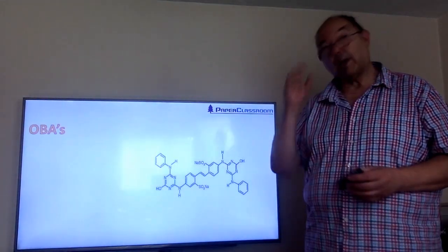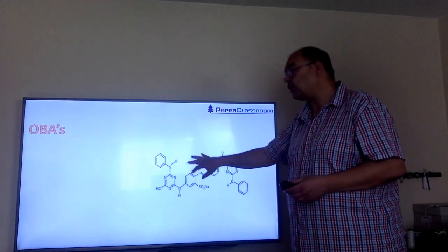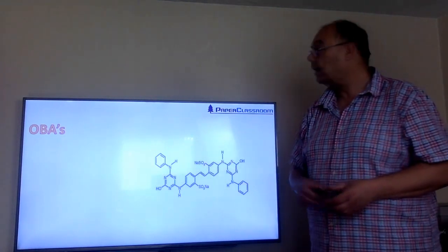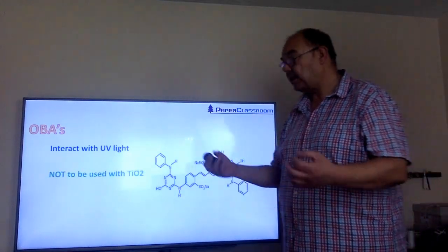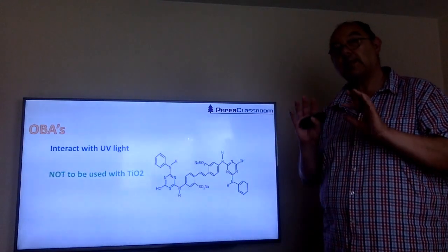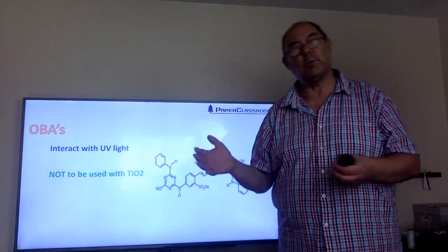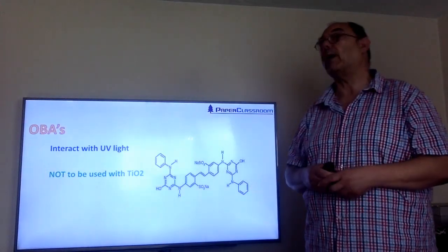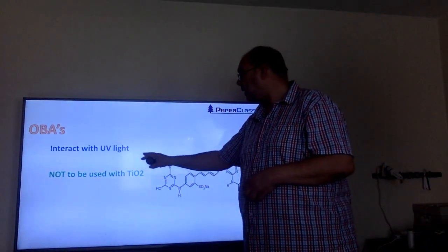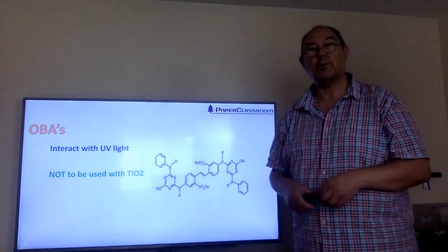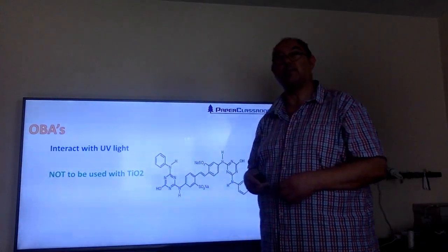And then we've got optical brightening agents. There's many different optical brightening agents. They're generally based on the stilbene molecule. And we know about OBAs, they interact with light. They bring in ultraviolet light and they re-emit it in the blue part of the spectrum. And the human eye confuses blue and white and makes things think they're whiter. As I mentioned previously, OBAs should not be used when you use TiO2 because the TiO2 will grab the ultraviolet light before the OBA gets an opportunity to.